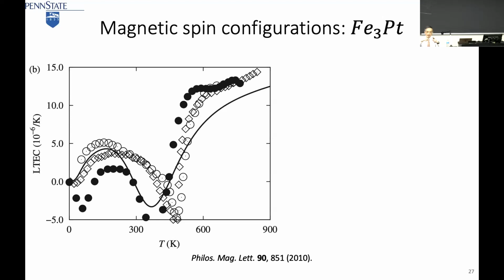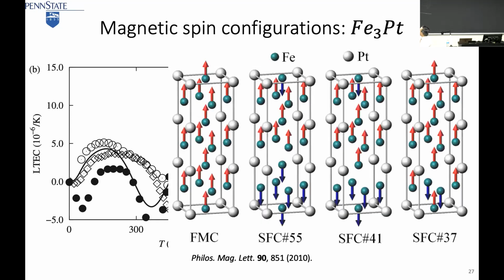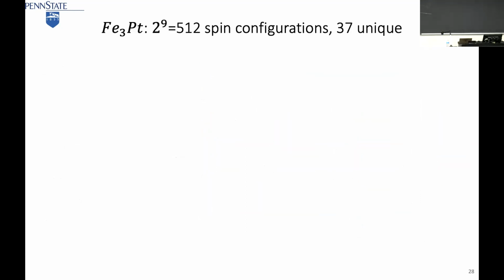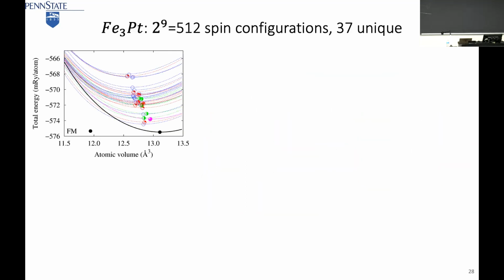But that's very small. So you make it bigger. You make it have 9 iron atoms. 2 to the 9 power will give us 512 configurations. But if you have symmetry, some 30-something of them are unique. Okay? So now, with 512 spin configurations and 37 unique ones, we calculate the energy at 0 Kelvin as a function of volume. That's standard DFT, very fast to calculate.